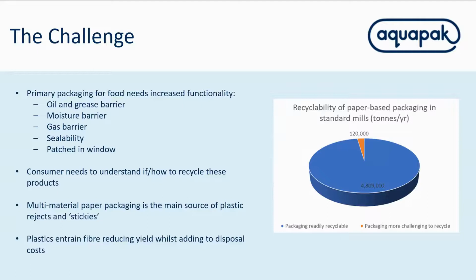So multi-material paper packaging, as we can see, can be a main source of rejects and so-called stickies. So that contamination from things like adhesives and coatings, for example, which, if they penetrate the mill chemistry, can interact with the paper recovery system and produce essentially reject material, or certainly below par material in terms of what's acceptable to both the mill and their ultimate customers. So clearly we need to come up with systems which, if you're going to increase this tonnage of material that a mill can cope with and is accepted, ideally give them some sort of economic commercial advantage.